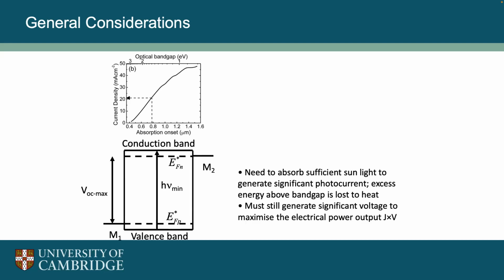But the problem is when we think about the open circuit voltage, which is the other aspect of the solar cell, we need as wide a band gap as possible, because essentially the open circuit voltage, or the maximum we can get, is dictated by the band gap, and in fact dictated by the difference in quasi-Fermi levels splitting between the electrons and holes. So this leads to a compromise.